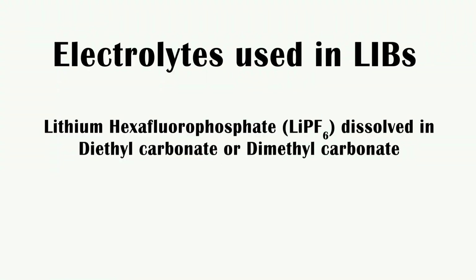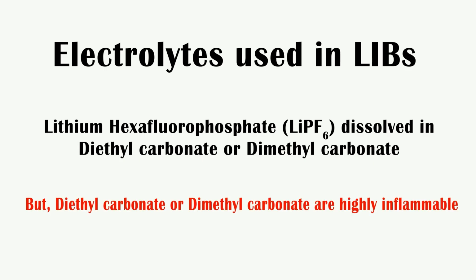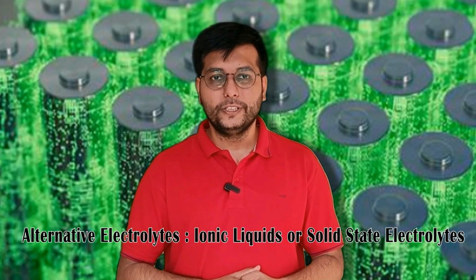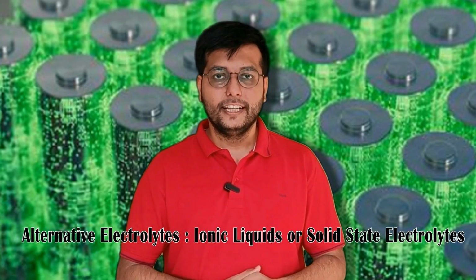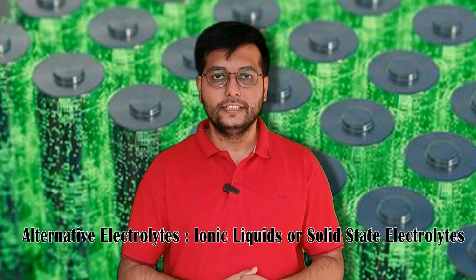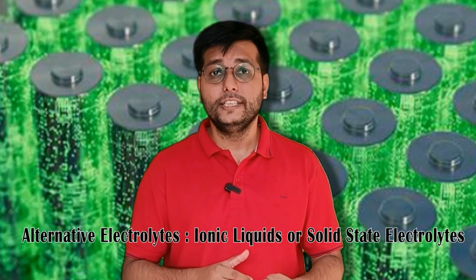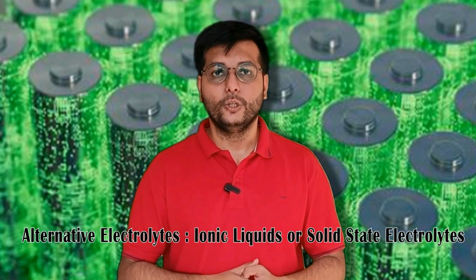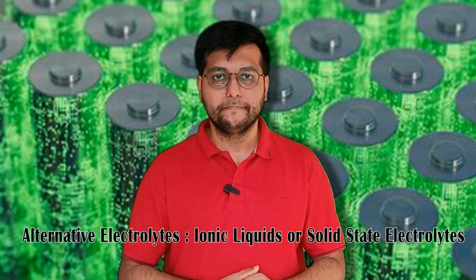Currently, lithium salts like lithium hexafluorophosphate dissolved in organic solvents like diethyl carbonate, dimethyl carbonate, etc. are used as electrolytes in the lithium-ion batteries. But unfortunately, these organic solvents are highly flammable and highly volatile, which may pose the threat of the battery's thermal runaway. Room temperature ionic liquids and solid state electrolytes like lithium lanthanum zirconium oxide can be good alternatives to these organic solvents as they are non-flammable and non-volatile.